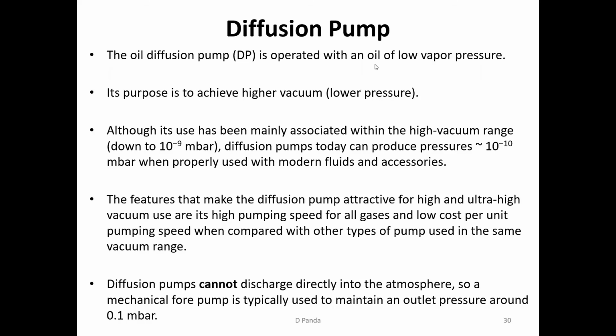The oil diffusion pump is operated with an oil of low vapor pressure. It is used for higher vacuum and lower pressure. It is associated with high vacuum, 10 to the minus 9 millibar, but it is usually very difficult to reach 10 to the minus 10 millibar. That can be achieved if we cool the system properly and use the proper fluids, that is, proper oil. And of course, the chamber: if we bake the chamber, cool the chamber properly, as well as cool the diffusion pump properly, we can achieve up to 10 to the minus 10 millibar. But it's definitely very difficult, and even 10 to the minus 9 millibar is not easy. We can achieve 10 to the minus 6 or minus 7 millibar very easily, but beyond this, it is very difficult.